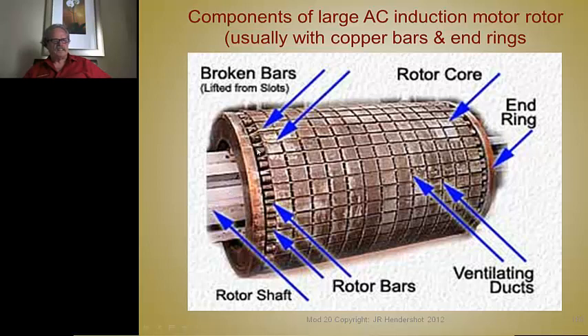See, when this spins, these extended blades here are there to eliminate bending, and due to thermal expansion and tangential shear stresses due to carrying the mass of the end ring, you allow these to be in bending instead of shear. And so it takes longer for them to work harden and crack and fail. That's why they extend them past the core like that. But this gives you the added benefit of a centrifugal fan in there to cool the rotor and the stator end turns that are right above this as well. So I guess that's all we need to say about that.